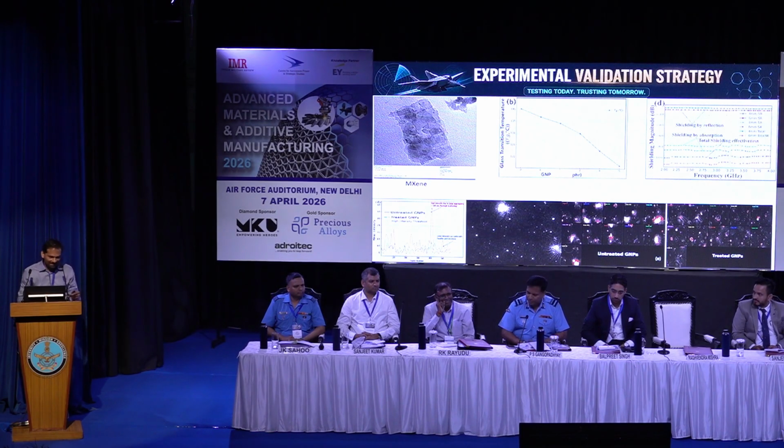Just finish. Okay. So this is the experimental validation. Here I developed the MXene-based material. Second, I used nano dielectrics. Mostly everyone knows that when we put nanomaterials in a polymer composite, Tg always increases, but here Tg is decreasing. That is the interesting thing, and it is created by nano dielectrics. Then third is the EMI shielding I measured, where the thickness varies in EMI shielding.